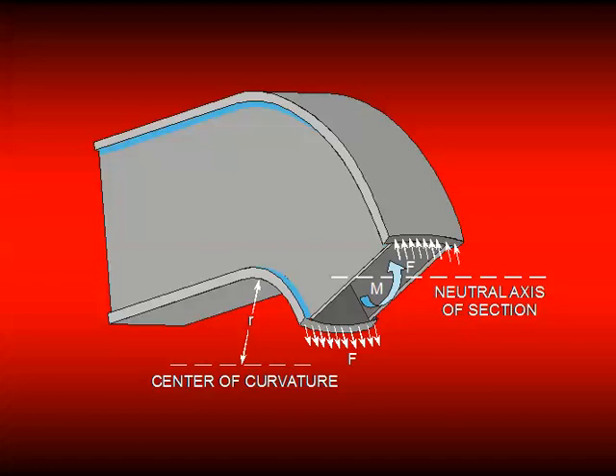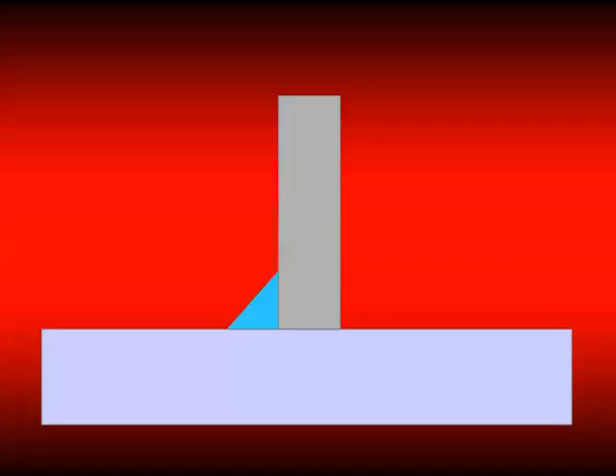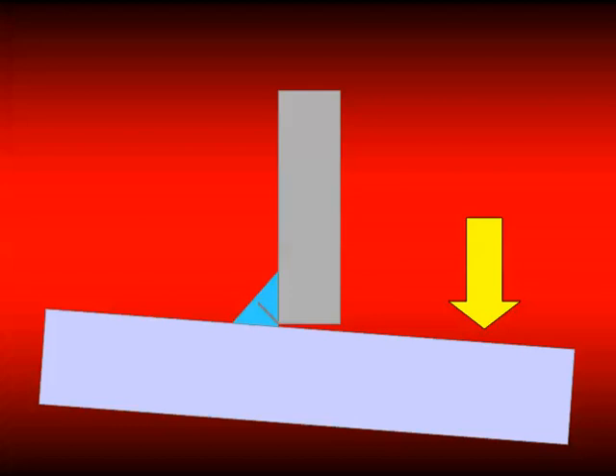Of course, the fillet weld has to curve around this knuckle area, subject to a bending load, and they find that the fillet weld in this area is cracking. It doesn't take too long until somebody analyzes and figures out what's going on. Here's the bottom flange, and as that's subject to bending, the center of that flange wants to break away. And it's putting this root of the weld into tension, and that's the little example that I gave you before of how easy it is to break welds if they aren't loaded in shear along their throat.